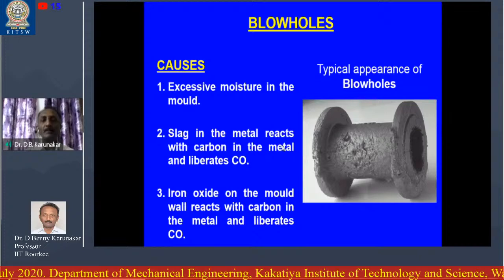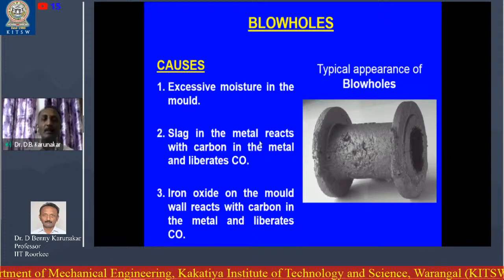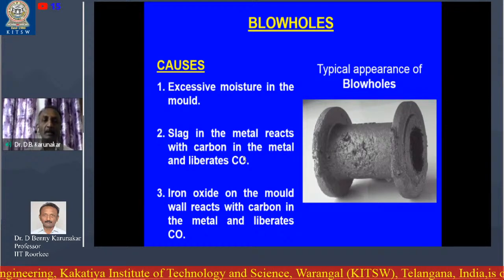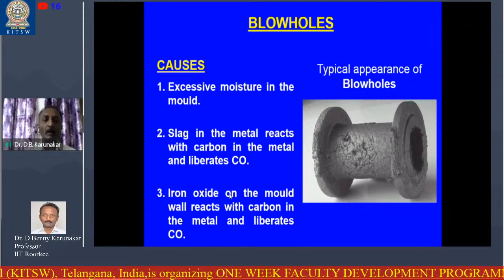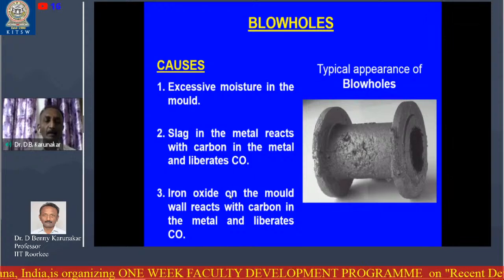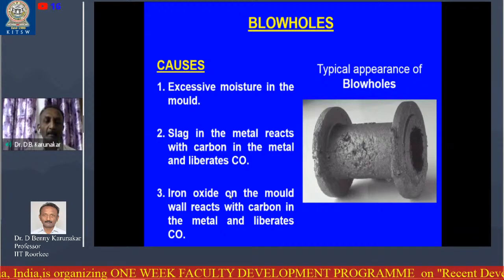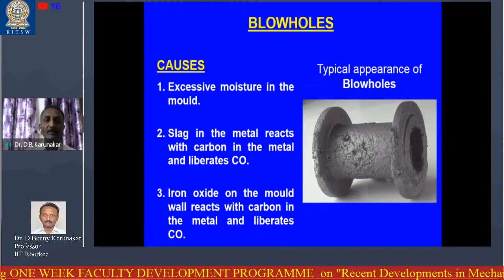Excessive moisture in the mold, slag in the molten metal reacts with the carbon and liberates carbon monoxide, and iron oxide on the mold reacts with the carbon in the metal and liberates gases. This is responsible for the blowhole defect.